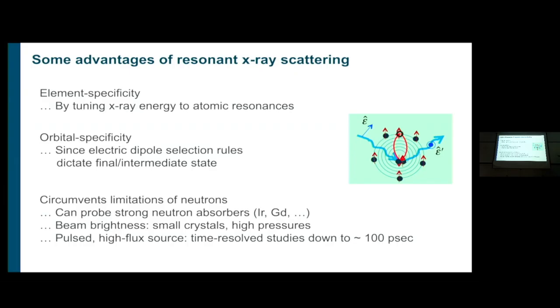So with this resonance, you're tuning the X-ray energy to a particular atomic resonance. This is an element-specific technique. If you have a material with many elements, you can pick up a signal from one particular element. The photoelectron lands in a particular orbital, so the technique is also orbital-specific, because the dipole selection rules dictate which L states couple. And it circumvents some of the limitations of neutrons because you can probe elements that are strong neutron absorbers like gadolinium or iridium. The beam brightness allows you to look at very small crystals, for example in high pressure cells. And as we said, the source is a pulsed source, so you can do time-resolved studies, for example pump-probe studies down to 100 picosecond time resolution.